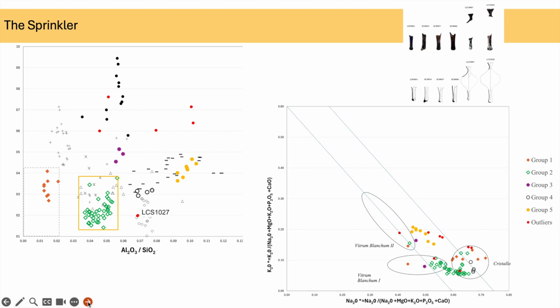So we have this idea that glass made in Portugal may have an alumina, so aluminium oxide content, high and very high. So we are talking about contents above 4, 6, 7 weight %, which is a lot for historical material. And so far we have not been able to find other glasses with this amount of alumina outside the Portuguese territory.